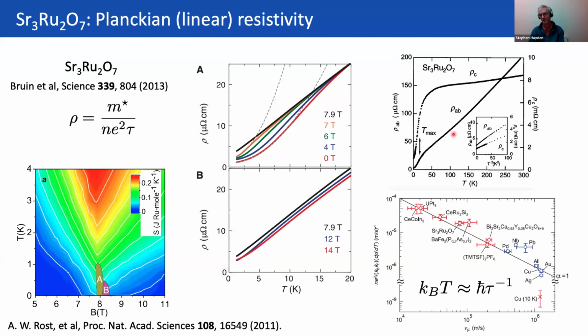If you go to higher temperatures in strontium ruthenate, the linear behavior actually goes on for a long time, just like in the cuprates. As you can see here, this is in zero field. This paper, from which these curves are derived, is a famous paper from Andy Mackenzie's group, and he showed that for a wide variety of systems, you could relate the scattering rate that comes out from a sort of Drude model for the resistivity to the temperature, and he found that they're similar if you compare different systems. This line here corresponds to these things being equal, and you can see strontium ruthenate is close to this line, and also this cuprate material he put on here, the 2212, is on the line. So I'll come back to that later on. This is the so-called Planckian dissipation.